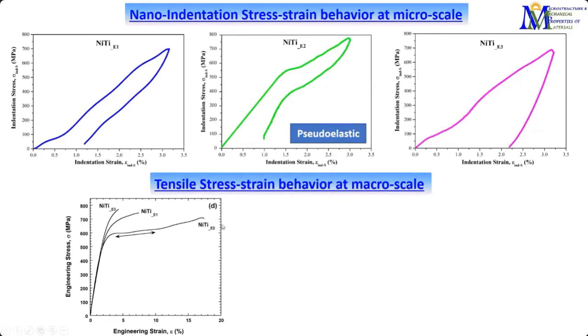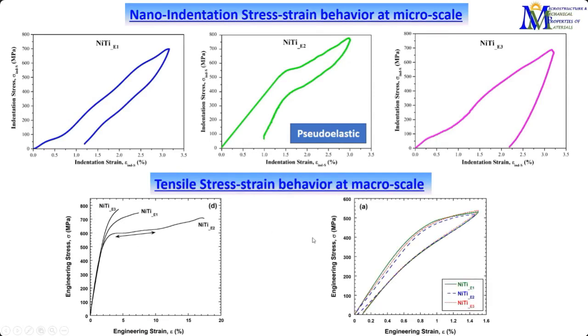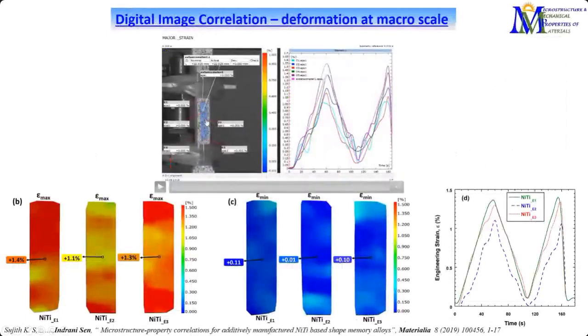We have also done bulk scale testing, and you can see that the one prepared with a moderate amount of energy gives us the nicest plateau and maximum ductility and so on. This has also been correlated with digital image correlation. While tensile testing, we figured out how the deformation is happening at every point. You can see that as we apply the strain, the color coding changes, signifying the amount of stress being applied, and this is loading and unloading, and then again loading.